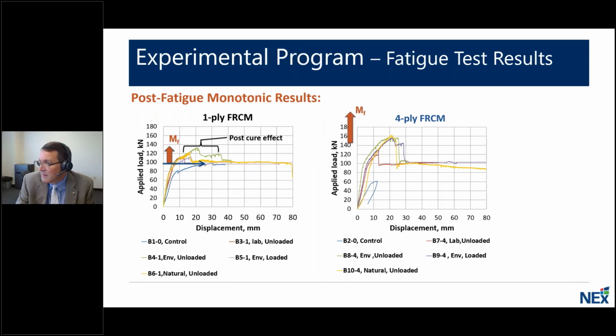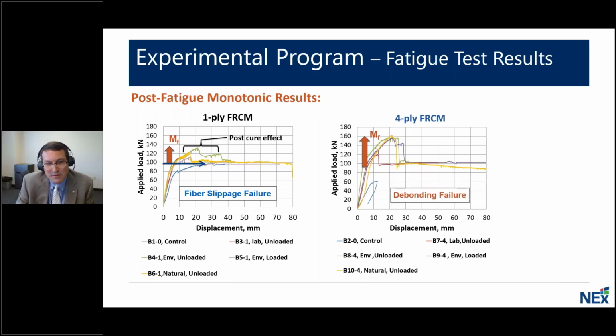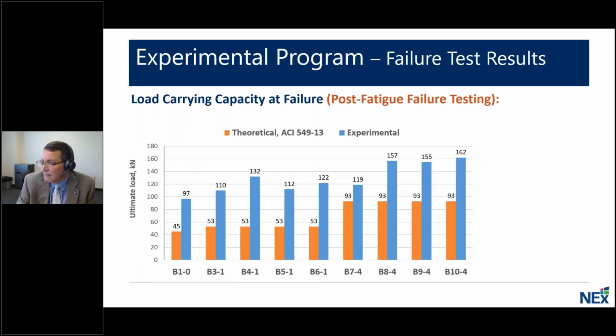In the 4-ply system, you can see that we also improved the strength carrying capacity when all of these beams were tested to failure after fatigue loading. But note that we do not receive a 4-fold capacity increase because these beams all failed by debonding. And so it's very important to note the difference in the failure modes for 1-ply versus 4-ply. In 1-ply, we see a fiber slippage failure versus a debonding failure. And I want to focus on this because towards the end of the presentation and webinar, we're going to talk about the importance of anchorage systems and how they can help delay that debonding failure for multi-ply systems where we would expect debonding failure to govern.